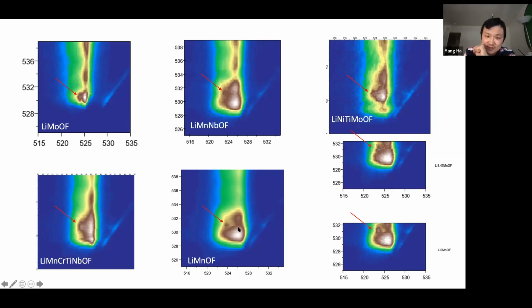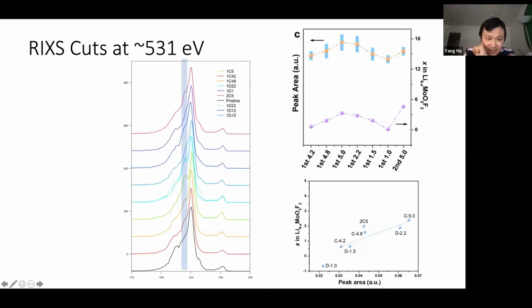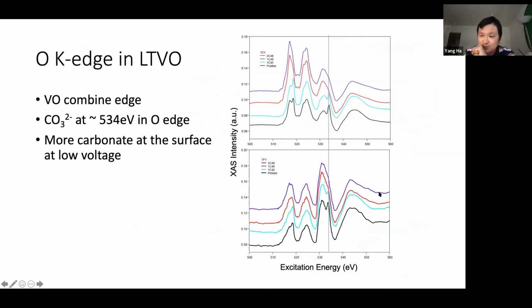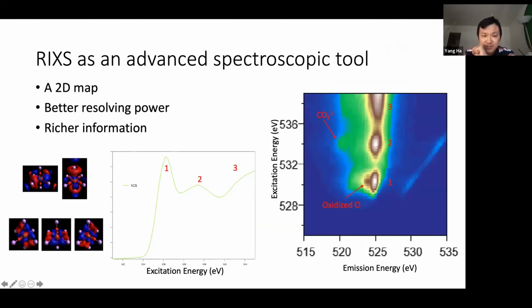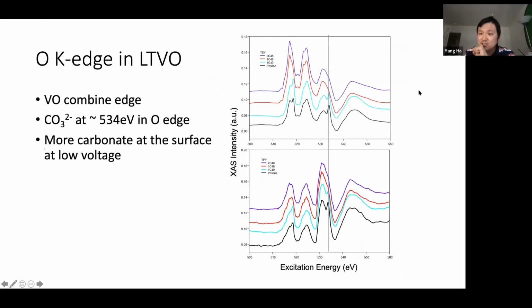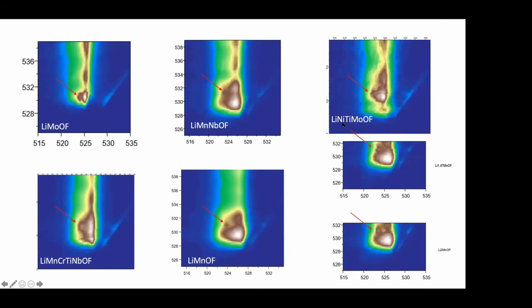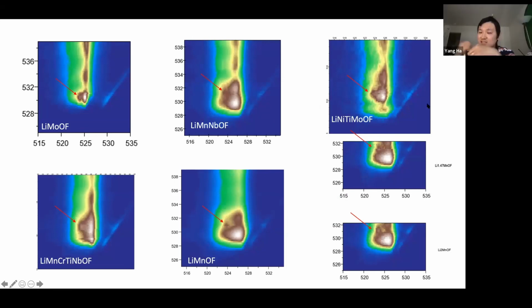oxide. So this is, I think I did a DFT calculation here. These two peaks correspond to the eg and the t2g set. And notice when you have more than one type of transition metal, when you have nickel and titanium and molybdenum, all these hybridization features tend to mix. So you will end up with something ugly.